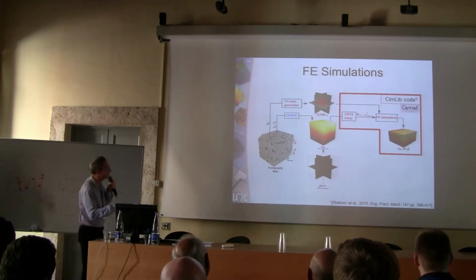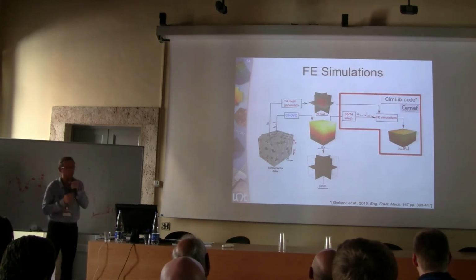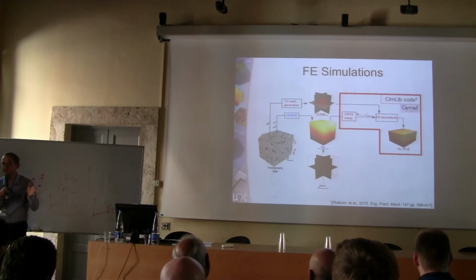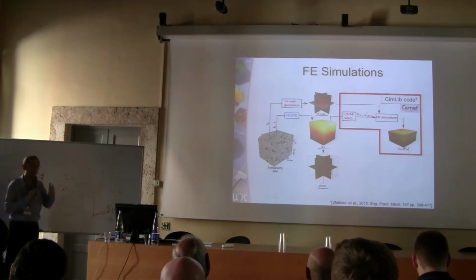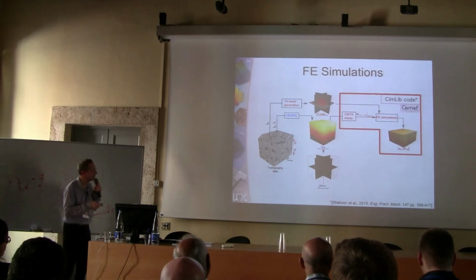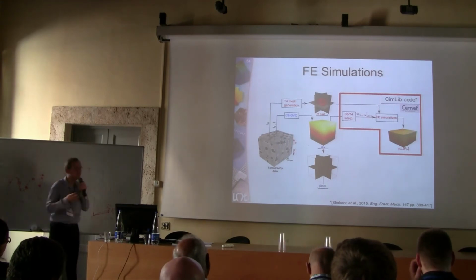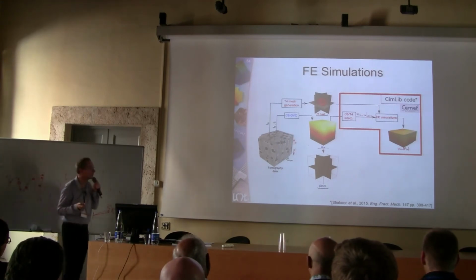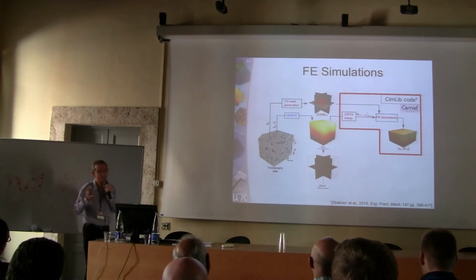And so that means in this particular case, what was done was to assume that the nodules were basically elastic and the ferritic matrix was elastoplastic with Ludwik's law. So a very simple law.